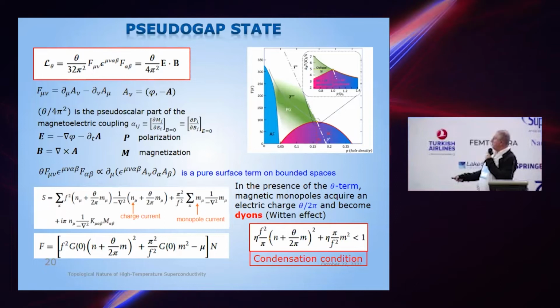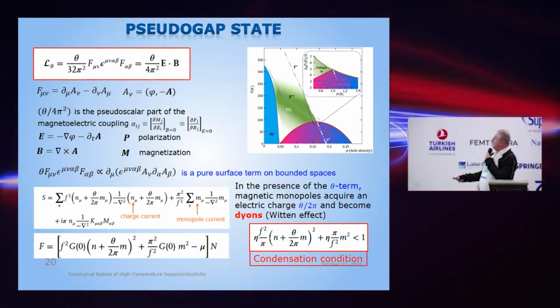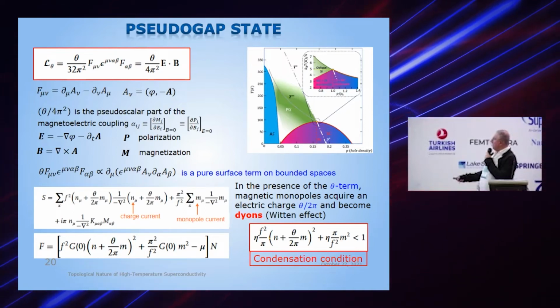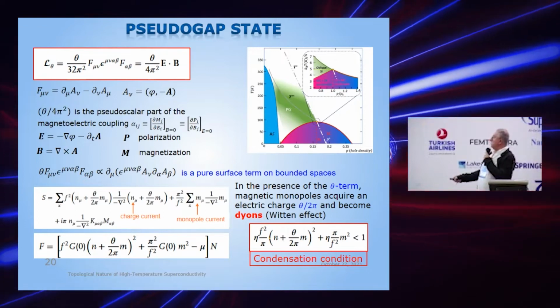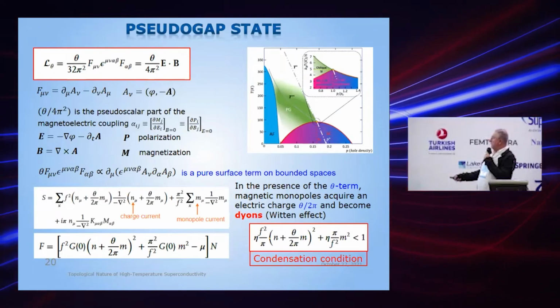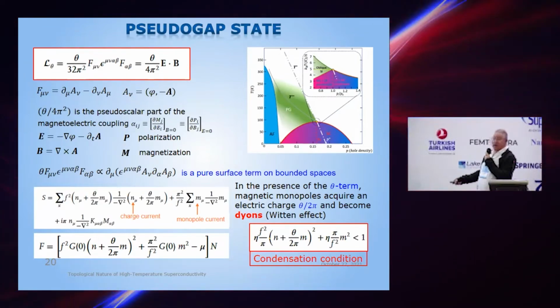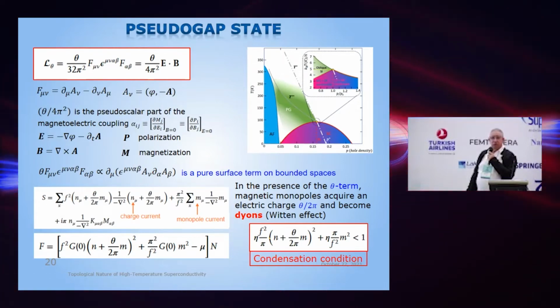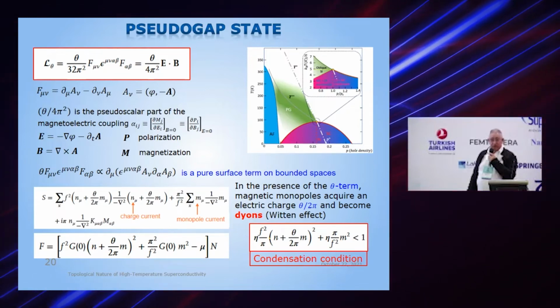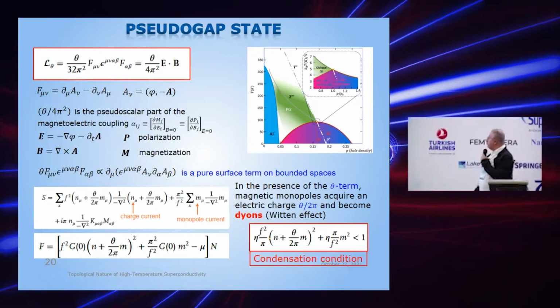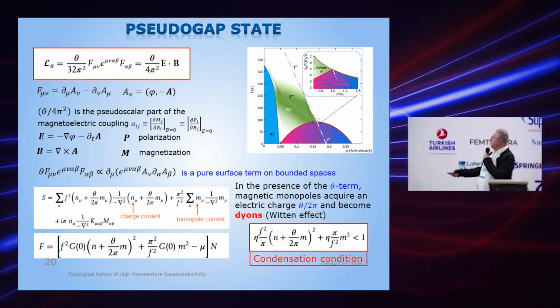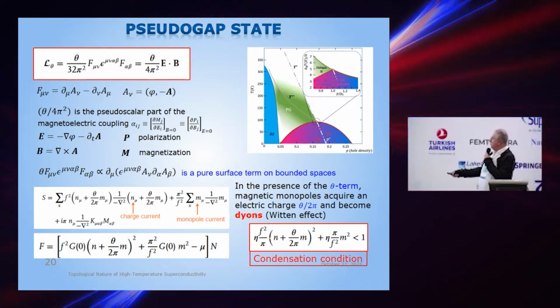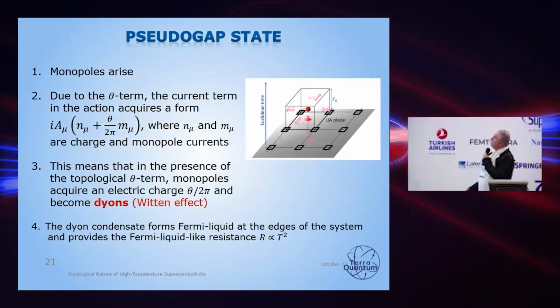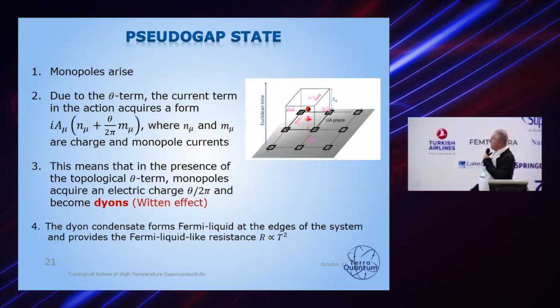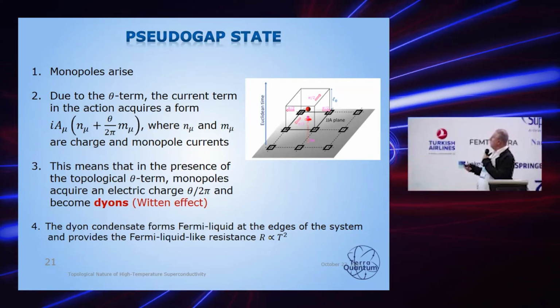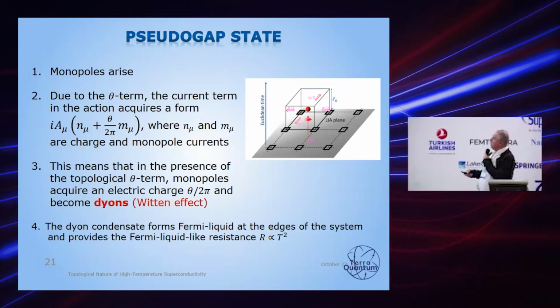And looking at this energy, we can immediately find the condensation condition. So it means that these two terms should fall within this ellipse. You understand? It means that either this term or that term makes the full free energy negative, and then the kind of carriers which makes the free energy negative causes boson condensation. So this is the condensation condition. So we can have either a dyon condensate or a monopole condensate, and depending on what happens there, we will have one or another state. And this is, once again, to remind you where monopoles are coming from.